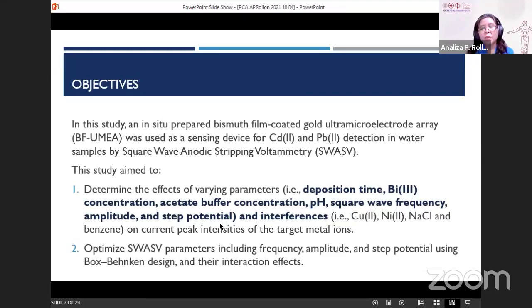And we also looked into the interferences of selected ions like copper, nickel, sodium chloride, and also benzene. We looked at the effects of these on the current peak intensities of the target metal ions. And we optimized the square wave anodic stripping voltammetry parameters, including frequency and step potential, using the Box-Behnken design, and looked at the interaction effects.